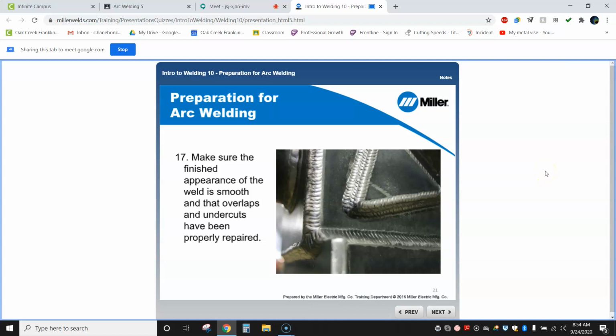Make sure the finished appearance of the weld is smooth and that overlaps and undercuts have been properly repaired. Overlaps and undercuts cause welds to fail in service if they exceed allowable tolerances established by code. Undercut, you guys, is where we have a section of metal that's been melted out but not refilled in. And then overlap is basically too much metal hanging off to the side. Those are both very bad, and they both need to be fixed before the weld can be sent out.